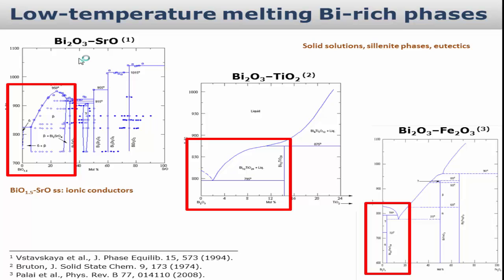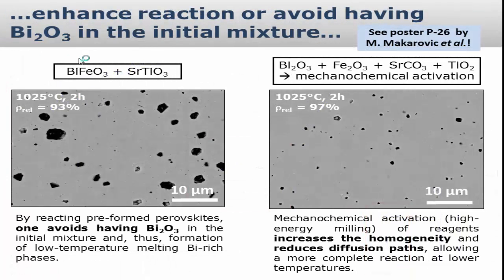It's a sort of rule of thumb that the temperature of a ternary eutectic is usually lower than that of a binary. So when you add components, you can really create very low eutectic temperatures, and this will then melt. If it melts before it reacts, it will create problems with this liquid phase around the grain boundary, which of course you don't want.